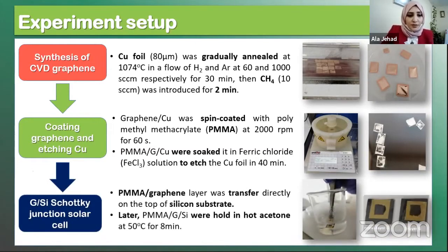So the last step was fabricating the Schottky junction. PMMA on graphene was transferred directly to the top of the silicon after etching the copper foil, and we left it to dry in vacuum, and after that we need to remove the PMMA layer. So we soak the cell in hot acetone for around 8 minutes, and after that it's dried again and was ready to make the measurement.